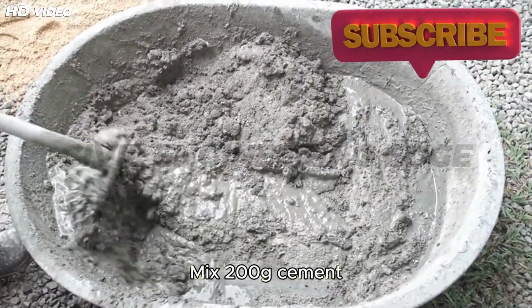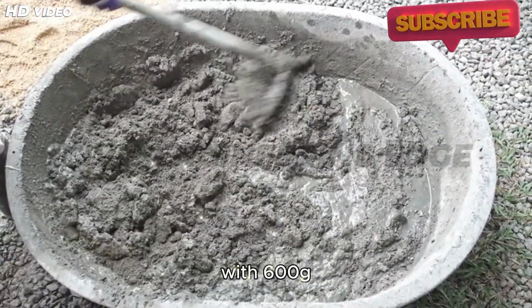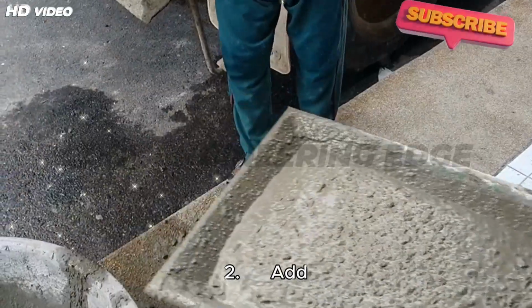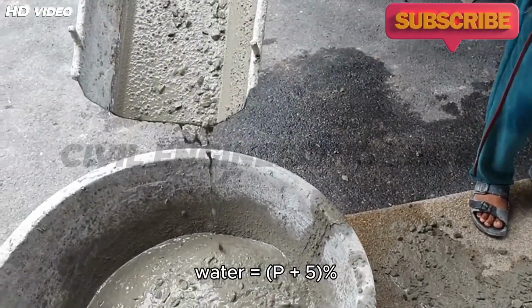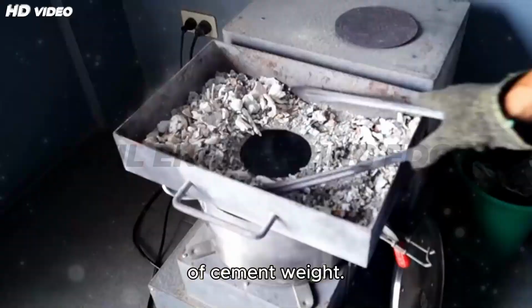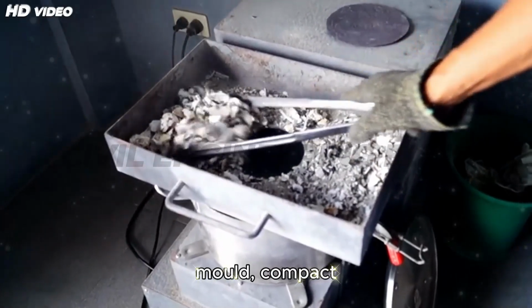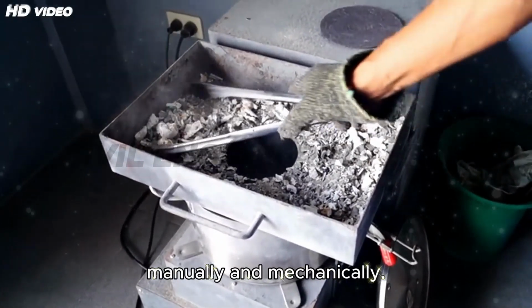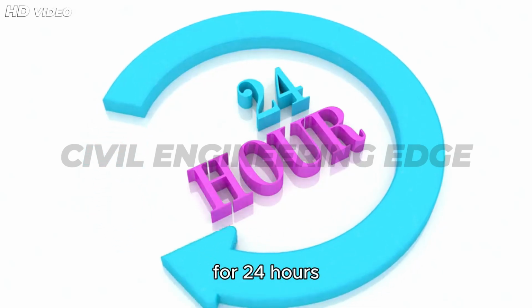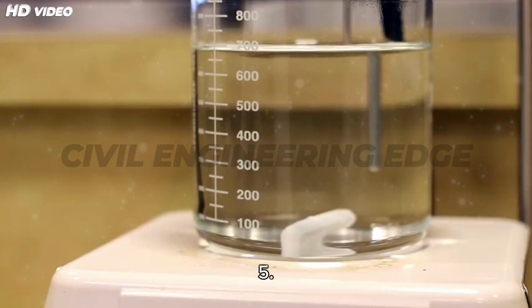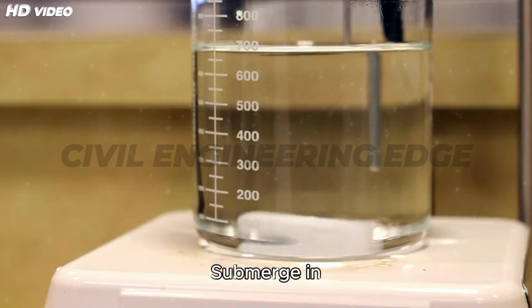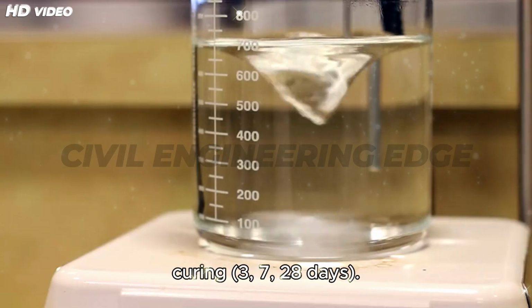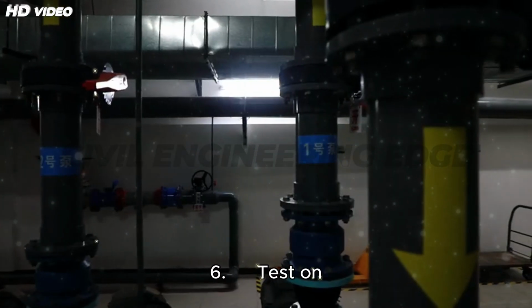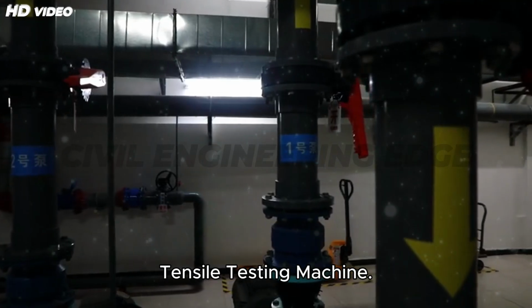Procedure: 1. Mix 200 grams cement with 600 grams sand. 2. Add water equal to P plus 5% of cement weight. 3. Fill the briquette mold, compact manually and mechanically. 4. Store for 24 hours in humid air. 5. Submerge in water for curing, up to 28 days. 6. Test on a tensile testing machine.